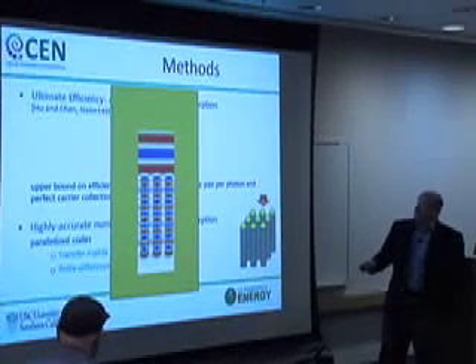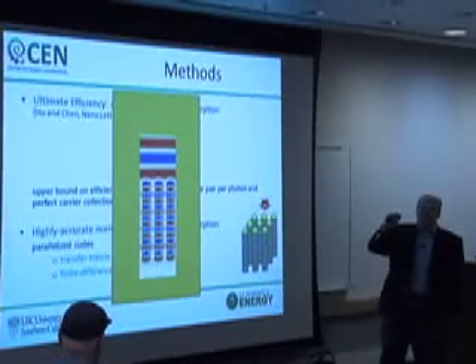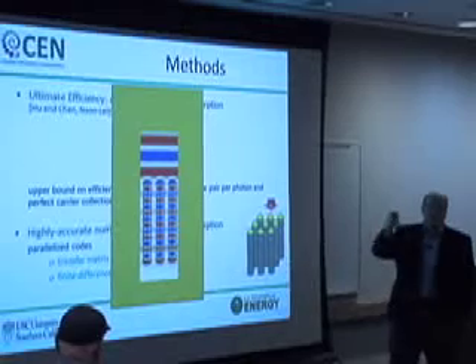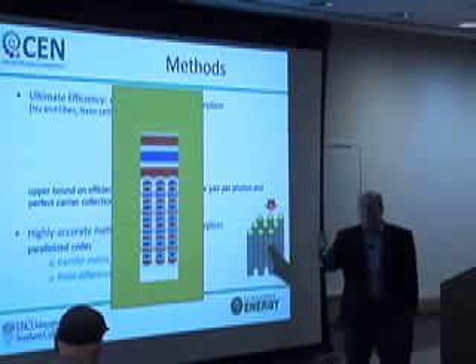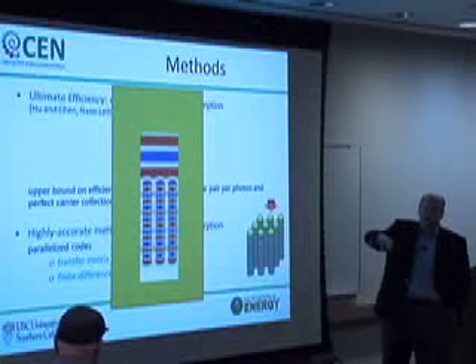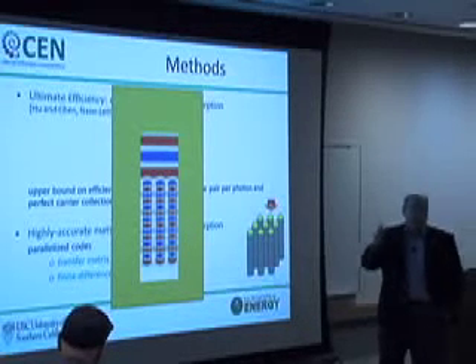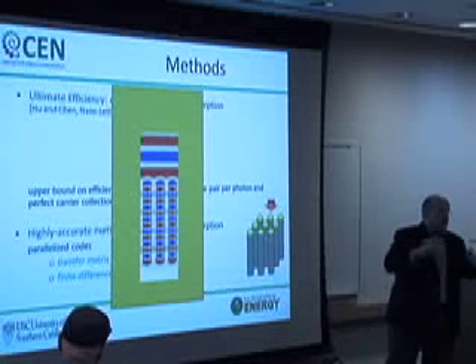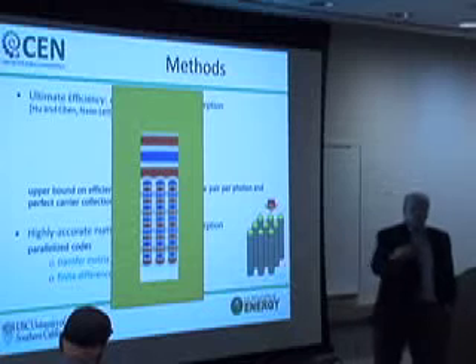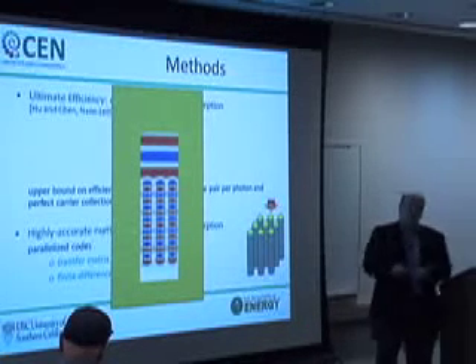One is that because of this light concentration, the height of these nanorods need not be any greater than the thickness of a film that you would put there to absorb an equivalent amount of light. So, for example, gallium arsenide has an above band gap absorption coefficient of 10^4 reciprocal centimeters, and in order to absorb 95% of the light, you need something that's about 3 microns thick. Similarly, nanorods need only be 3 microns tall, provided that you have optimized the lateral geometry and the spacing to achieve the same amount of absorption. So what that means is that we gain about a factor of 10 in terms of materials usage. And that's always an issue when you talk about large-scale usage of solar energy, because the materials we're dealing with here are not particularly abundant materials.